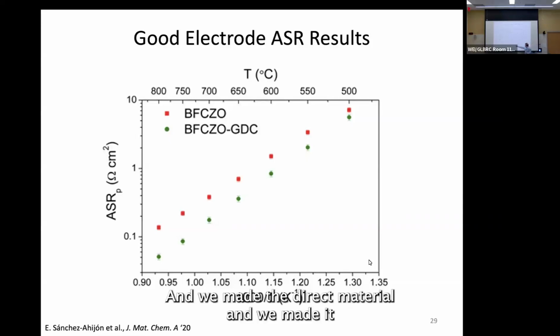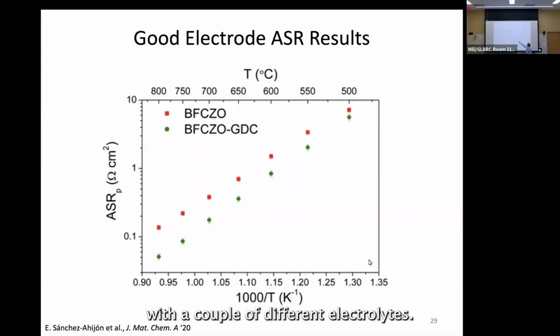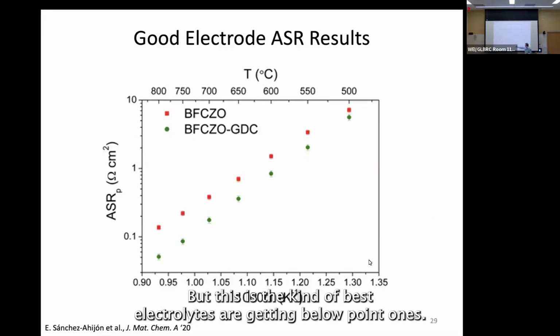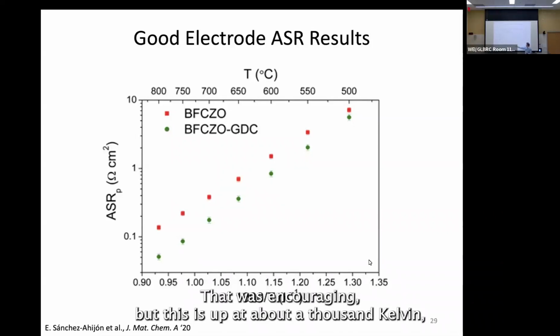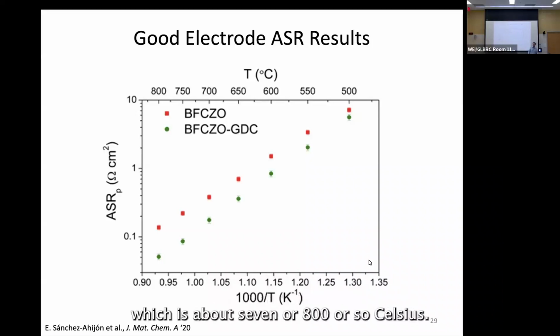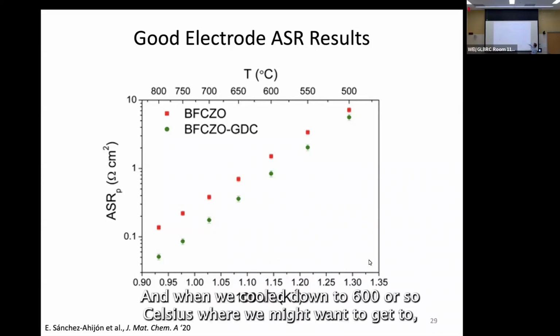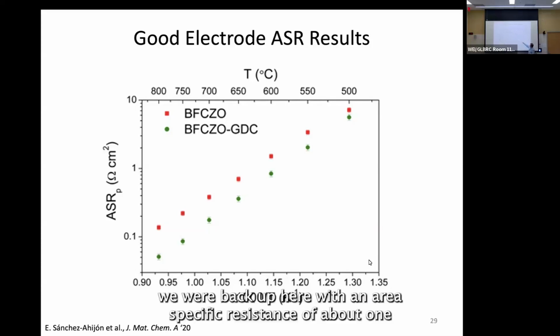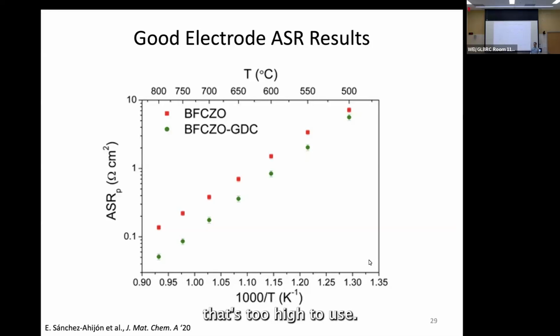And we made the direct material with a couple of different electrolytes, but this is the best electrolyte, getting below 0.1, so that was encouraging. But this is up at about 1,000 Kelvin, which is about 700 or 800 Celsius. When we cool down to 600 or so Celsius, where we might want to get to, we were back up here with an area-specific resistance of about 1. That's too high to use. So the material seemed encouraging, but wasn't really performing the way we had hoped.